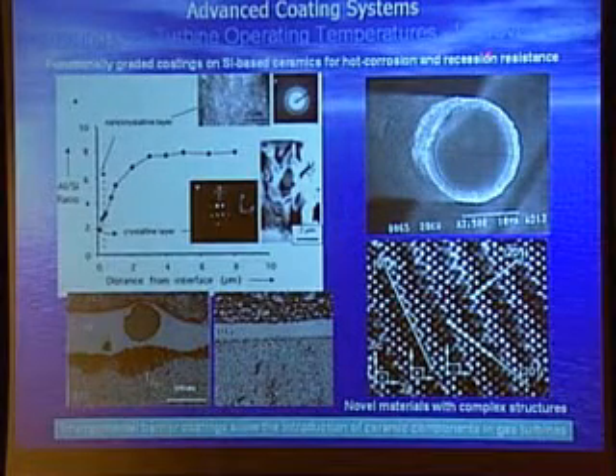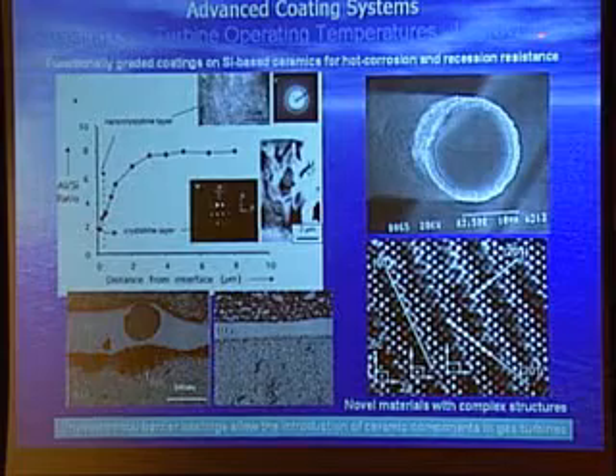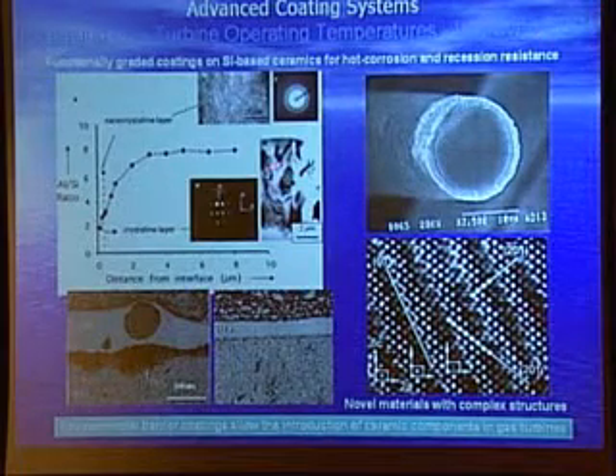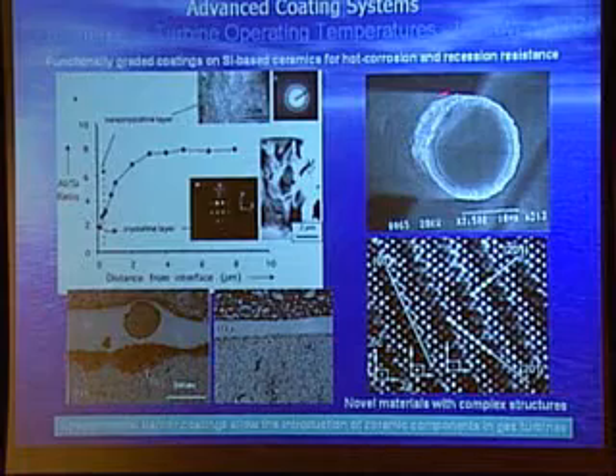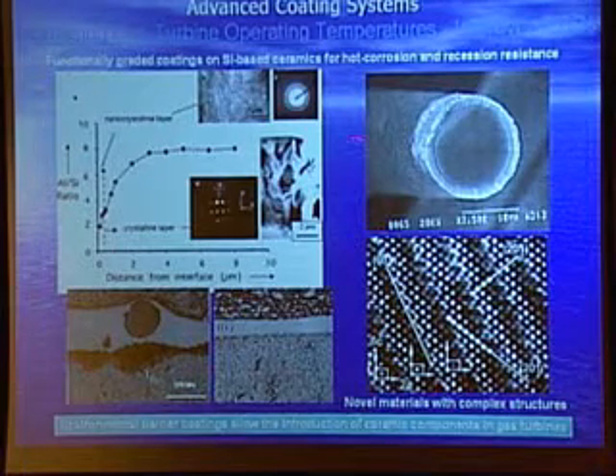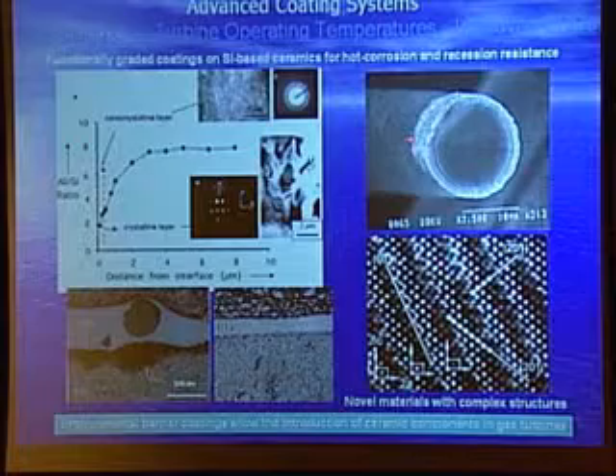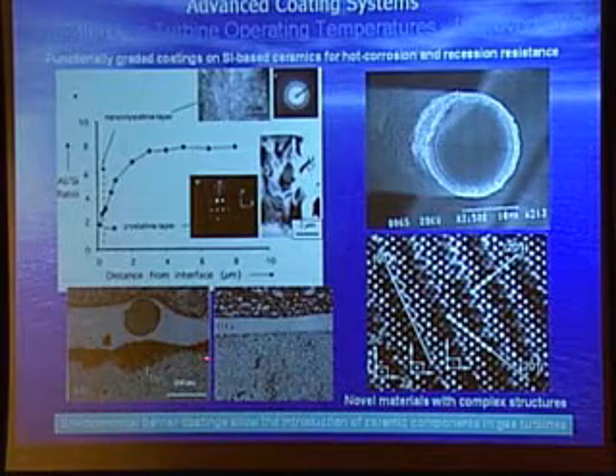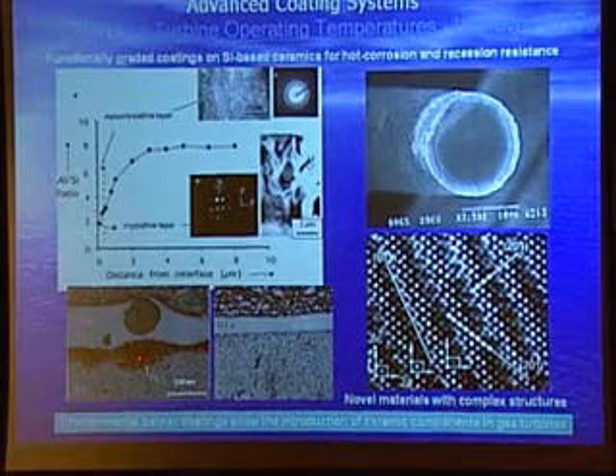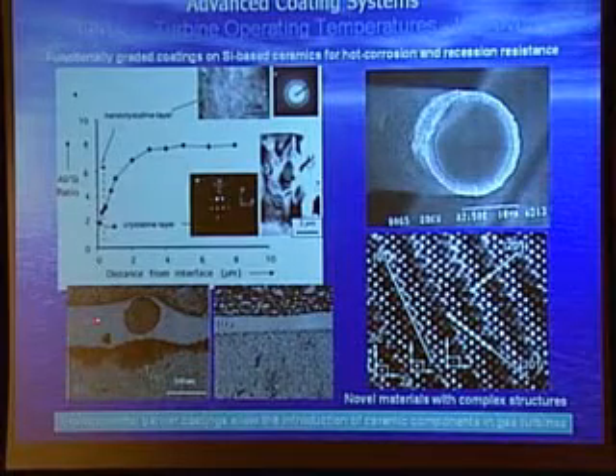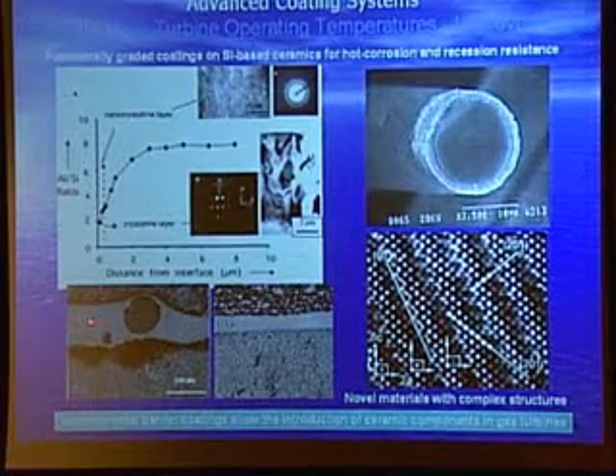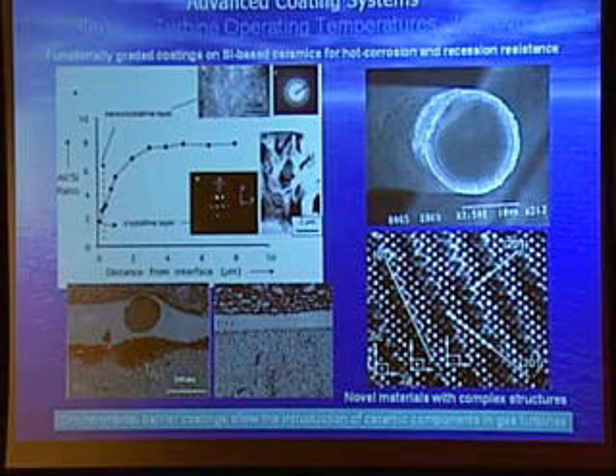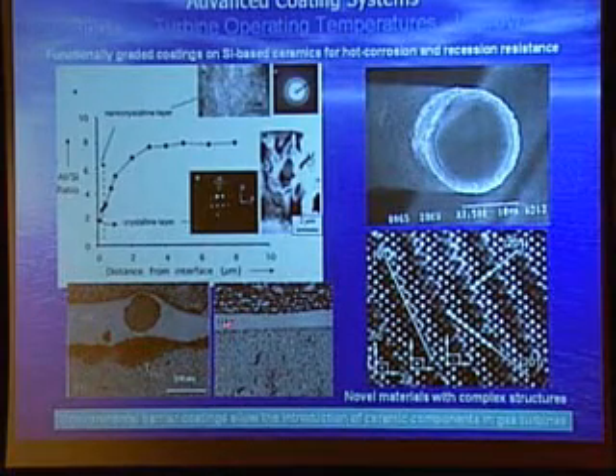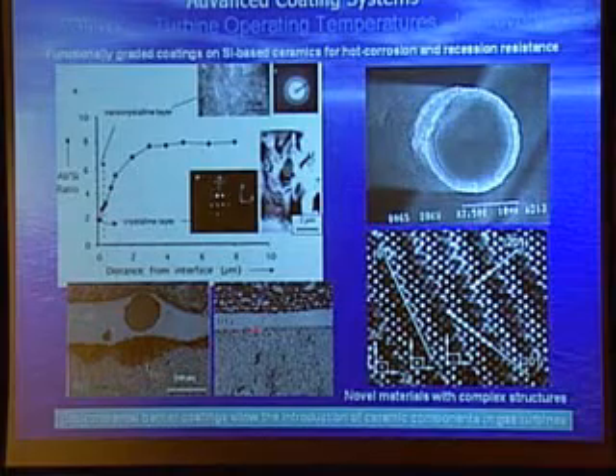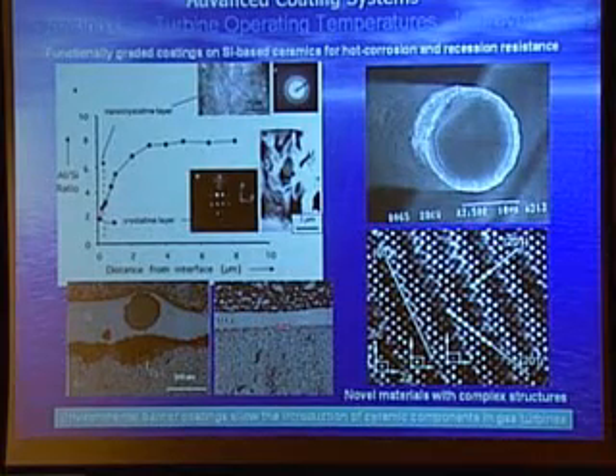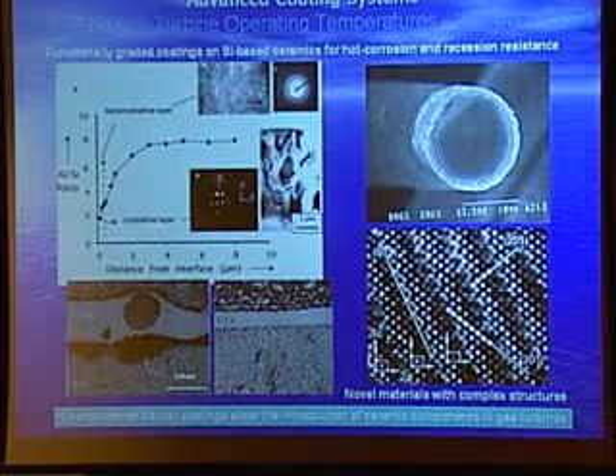So we are also developing environmental barrier coatings. And here in this slide, you can see such a coating, which is a functionally graded mullite deposited on a silicon carbide substrate. And you can see when the coating is not present, the surface gets attacked by the environment, which in this case is slag, and you can see the formation of the pits. And by having even 1 to 2 microns of the coating, you can see that the substrate is adequately protected.